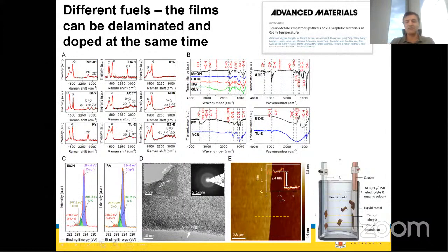We just paint the liquid metal on the surface of copper or any other metal. You apply the voltage, it forms, but it doesn't deform the surface. And because of electrophoresis, it can attach itself, go to the other side, and land on the substrate that you want. It's a perfect graphitic material, actually. It's very highly crystalline graphene oxide. And interestingly, if you use a fuel that includes nitrogen, you get nitrogen-included graphitic material. As you may know, graphene with added nitrogen, nitrogen-doped graphene, has a very strong catalytic property.